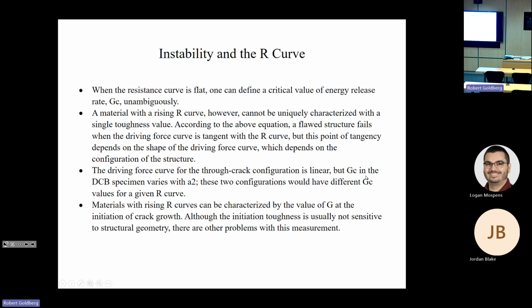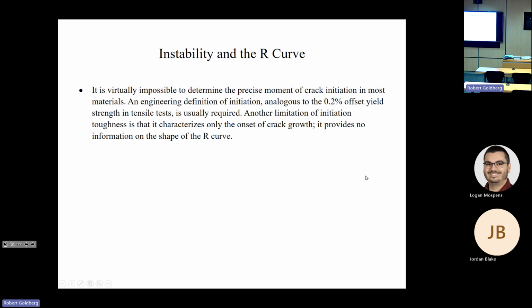And this initiation toughness is usually not sensitive to structural geometry, but there are other problems with this measurement. One of the big ones is that for most materials, if you're doing a fracture test, it's hard to determine the precise moment of crack initiation. We'll talk about this later in the semester when we talk about test techniques, but there is an engineering definition of initiation, similar to the idea that when you do yield analysis of metals, you probably learn that you use a 0.2% offset, that you say that the yield stress occurs when you have 0.2% plastic strain. And so that's one way to look at it.